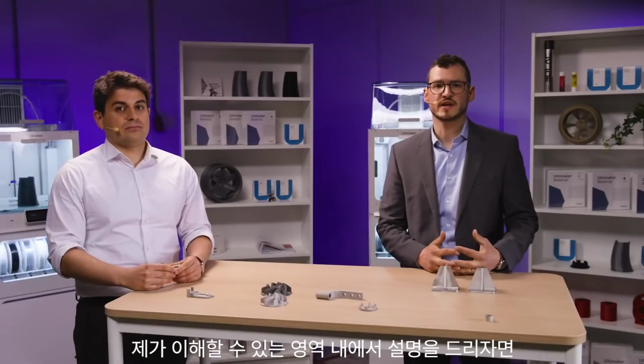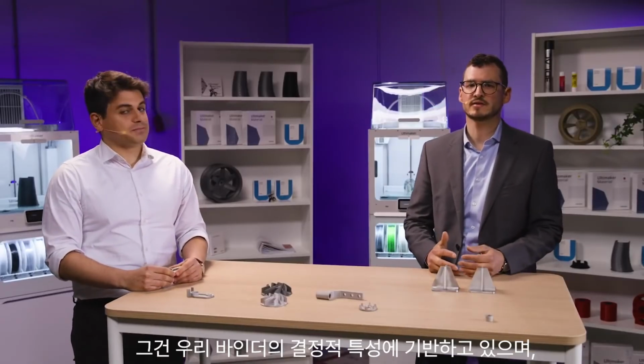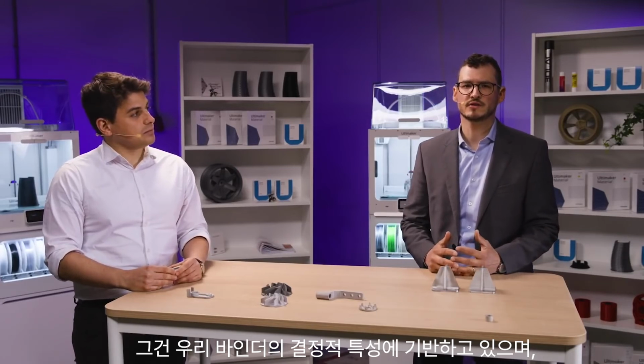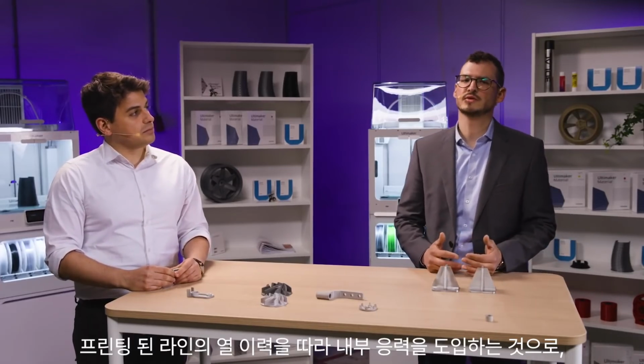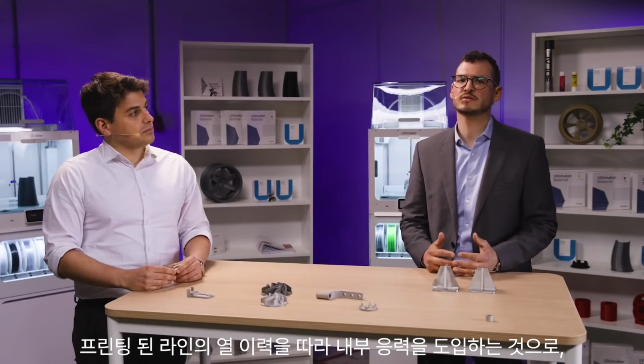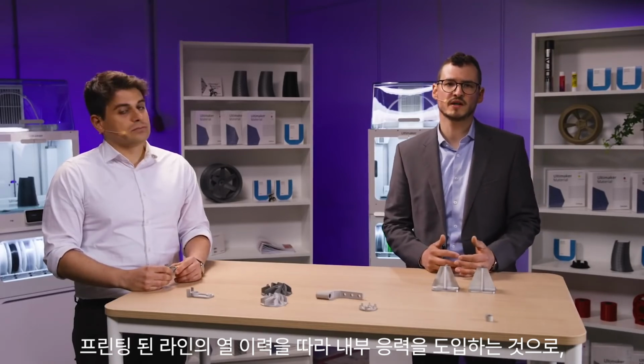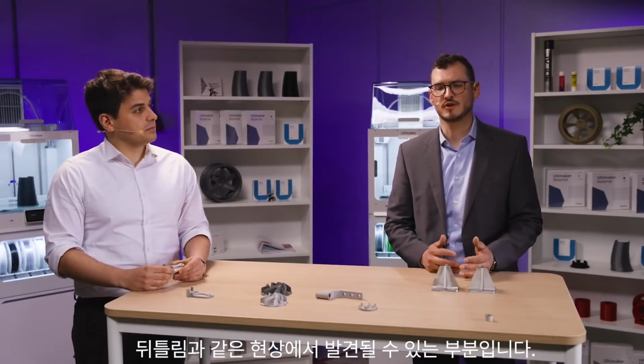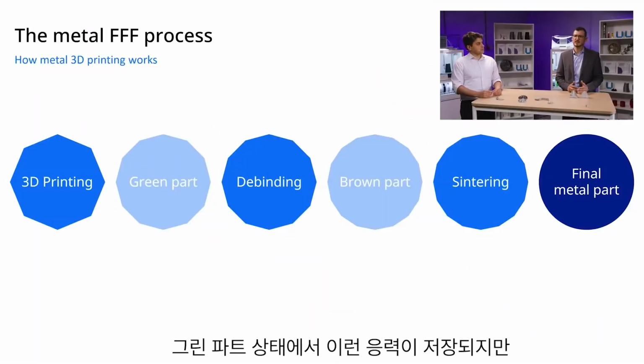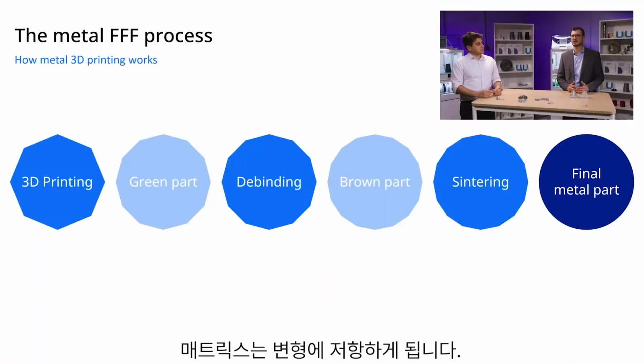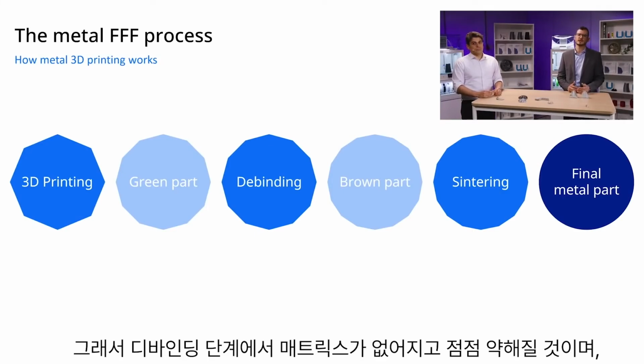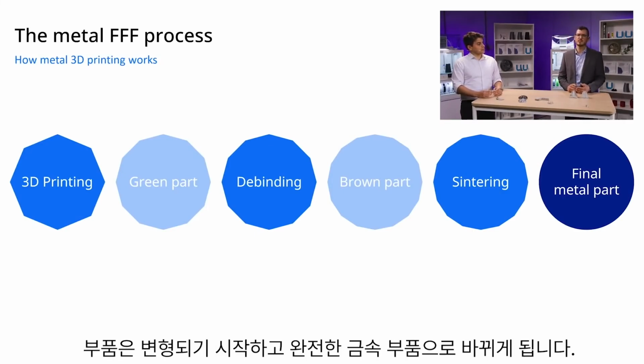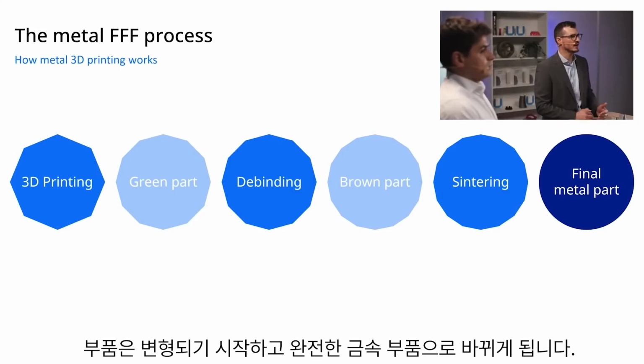As far as I could understand it, it's based on the crystalline character of our binder, which introduces internal stress along the thermal history of the printed lines in the part, which could also be seen in phenomena like warpage. In the green state, these stresses are stored, but the matrix resists the deformation. So during the debinding steps, the matrix is removed and gets weaker, and the part starts to distort, and the shape is transferred into a full metal part.